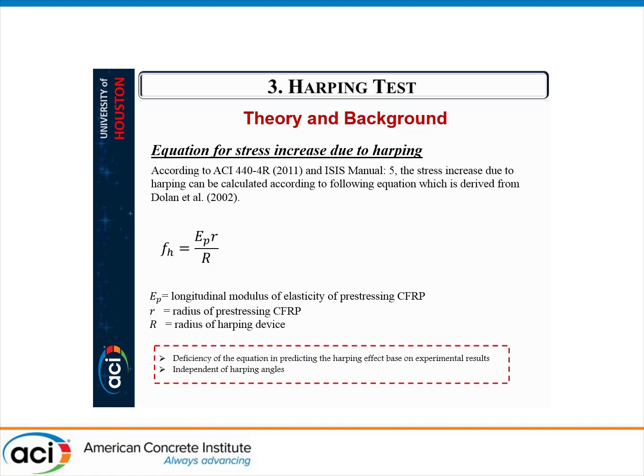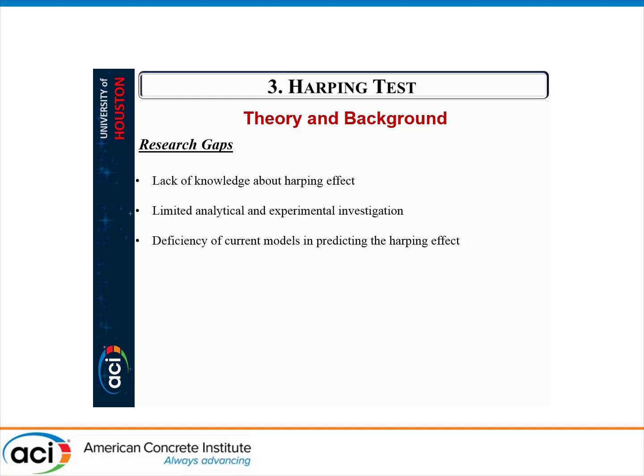And the current equation mentioned in ACI 440 is not very accurate to calculate the reduction of tensile capacity. As you know, this equation is only a function of modulus of elasticity, radius of the tendon, and radius of deviator. And there is no sign of harping angle in this equation. The assumption behind it is that the radius of deviator is the same as the radius of curvature of a harped tendon, which is not the case. By applying the prestressing force at different harping angles, it can be changed. So this portion requires more attention. So the research gaps are the lack of knowledge about the harping effect, limited analytical and experimental studies, and deficiency of current models in predicting the behavior.